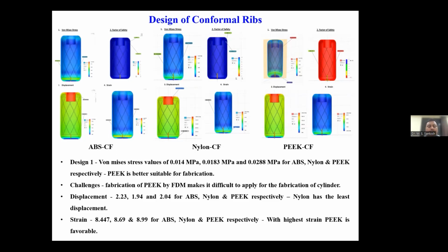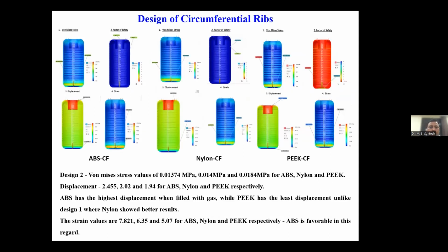And in that journey, we could identify that although there was some amount of displacement seen for nylon and ABS also, nylon appears to be a more suitable material. When we say nylon, it is nothing but polyamide materials. Eventually, the circumferential patterns or the hoop stress associated with the cylindrical liners were the ones that play a significant role in bearing the required pressures within the ABS and associated nylon or PEEK materials.